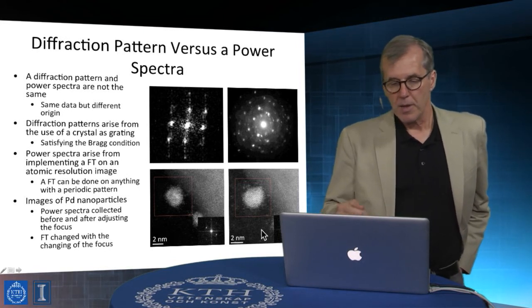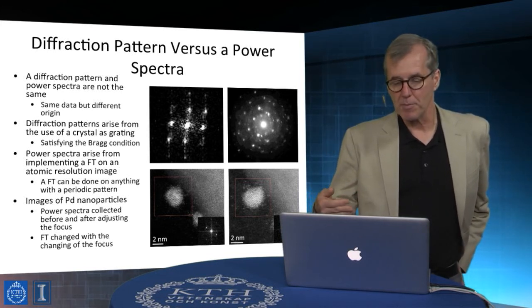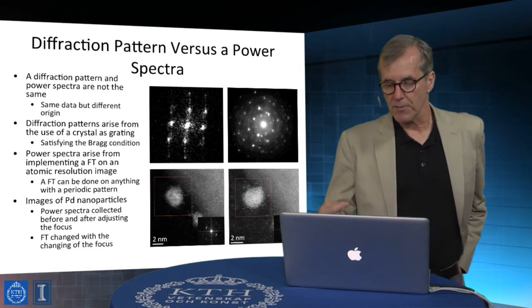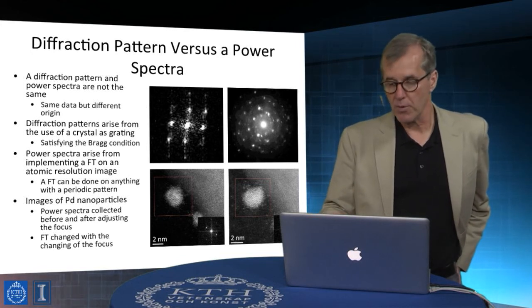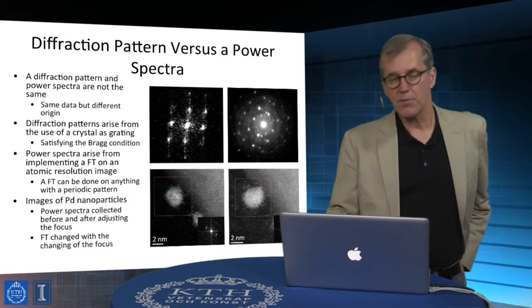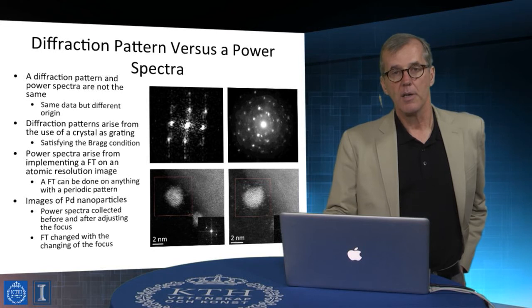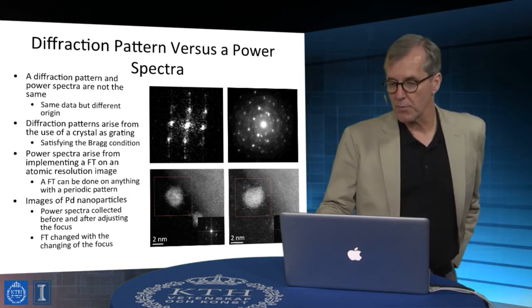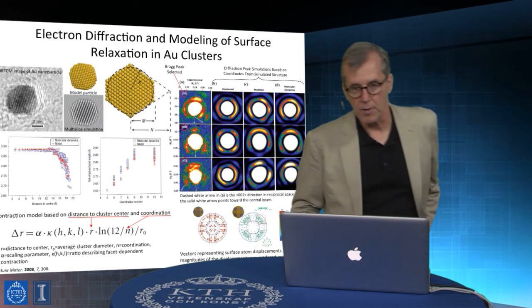Except that power spectra also are probably less powerful than a real diffraction pattern because they are impacted by the resolution of the instrument, right? So they can give you an incorrect understanding, or at least a less clear understanding of what the atomic ordering might be like. But again, it's a useful form of measurement.